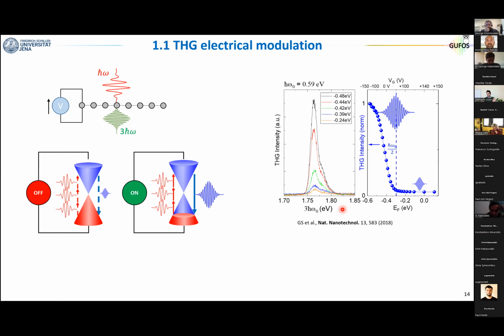So this trick of using resonances only works in atomically thin materials, so graphene and TMDs, because there the reabsorption is close to zero. So exploiting the resonances is, of course, one way of enhancing the nonlinearities, which is known also for bulk materials, but you cannot apply it to bulk materials, right? You can only apply it to TMDs or to 2D materials.